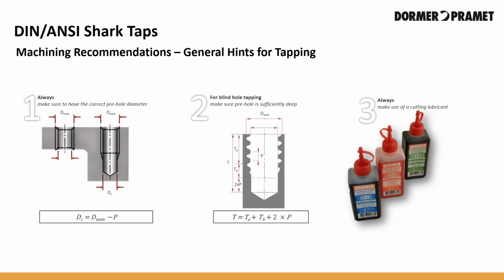When a tap breaks, it's almost always a result of the torque becoming too high. During the lifespan of a cutting tap as well as a forming tap, the torque increases as a result of the tap's cutting edges getting dull. It is recommended to use tapping attachments that are equipped with a safety clutch to prevent breakage and to allow the user to safely use a tap to the end of its tool life. When pre-drilling for blind holes, we recommend including a safety distance of at least 2 extra threads at the bottom of the hole. If a tap hits the bottom of the hole when tapping, the tap will definitely break.